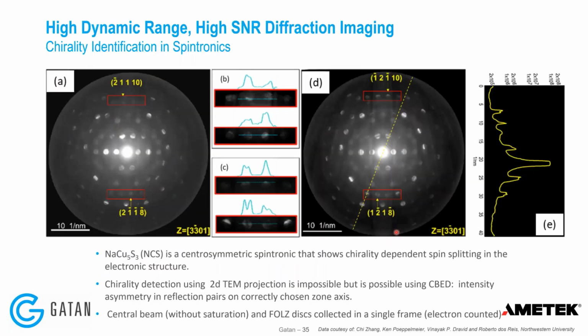Here is an example of using the high dynamic range of the camera, looking at this material, NCS. What happens is that the chirality in this type of material affects its electronic structure. Unfortunately, it's not very easy to detect or image chirality in bright field imaging. So what you can do instead is go to CBED mode and look at the inversion of the reflections of the diffraction pairs.